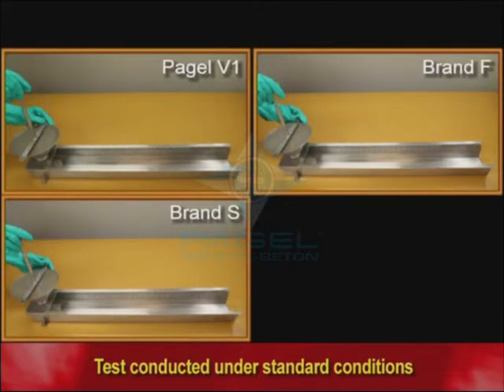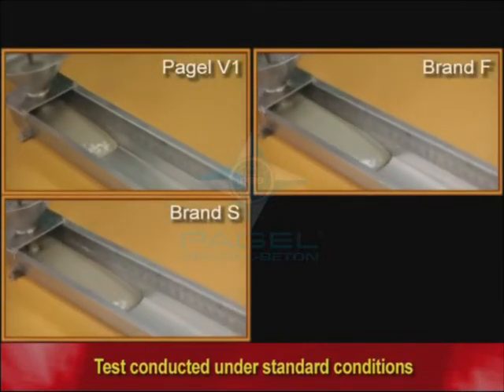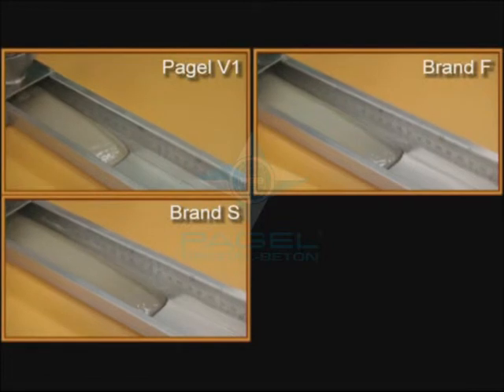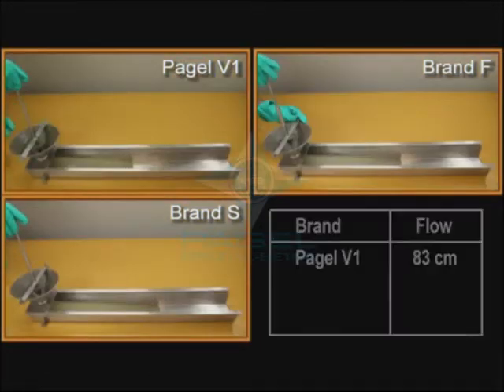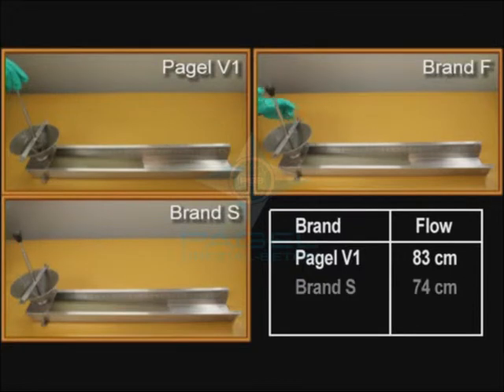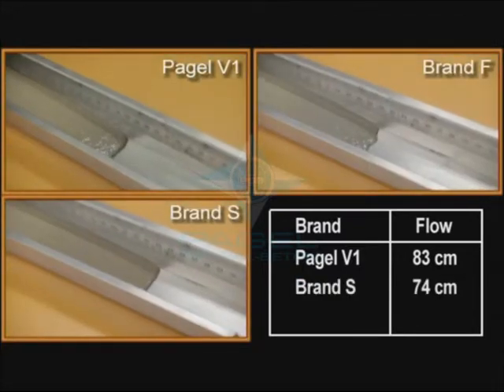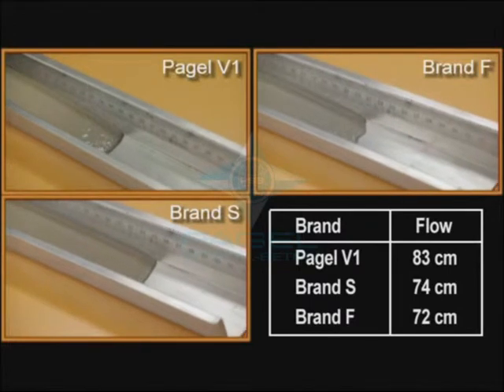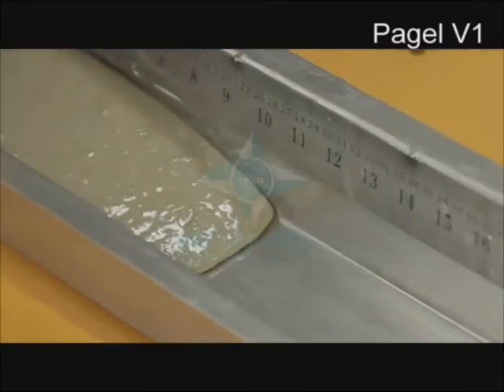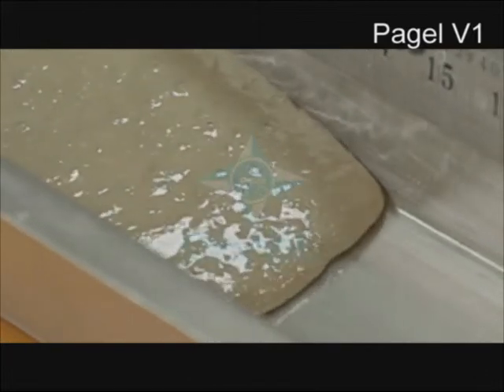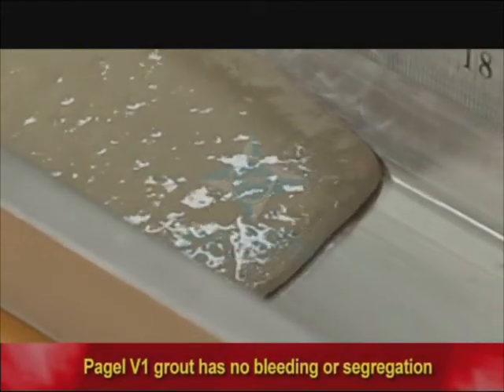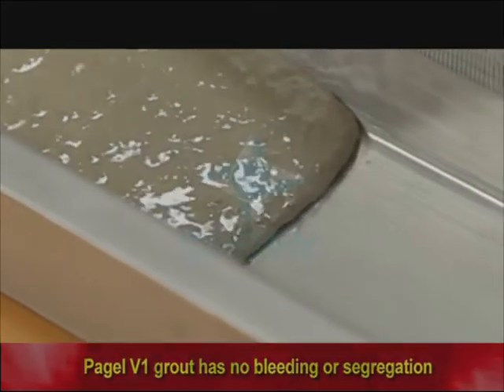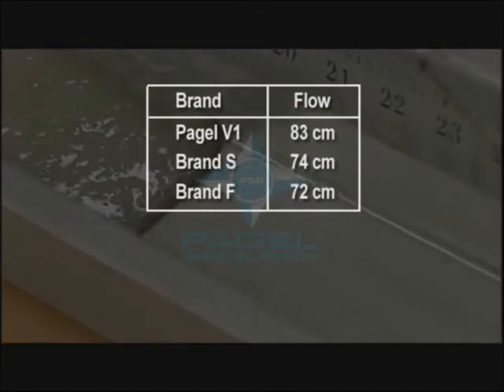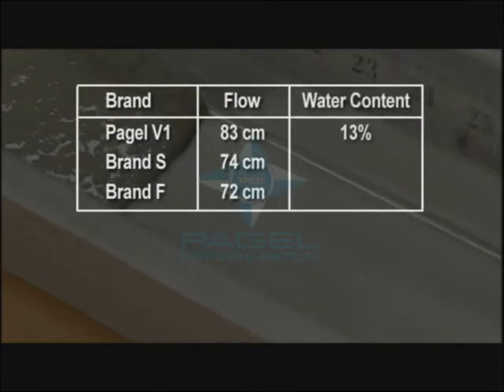While all the three grouts appear to flow well, you can clearly see that the Pagel V1 grout flows most smoothly and cohesively like lava and has a flow of over 83 centimeters compared to 74 centimeters for brand S and only 72 centimeters for brand F. And even though the flow of Pagel V1 is higher, there is no bleeding or segregation in spite of higher grain size. The main thing is that Pagel V1 achieves superior flow with addition of only 13% water.